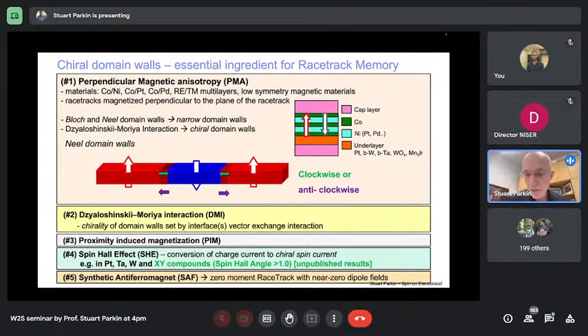That means supercurrent flowing through platinum has a critical current density beyond which it is no longer superconducting, which is different when the current flows from a left to a right niobium electrode placed above the platinum than when it flows in the opposite direction. So this is very exciting. We're doing a great deal of work on proximity-induced superconductivity to create triplet supercurrents that could carry spin angular momentum and therefore enable us to manipulate magnetization at cryogenic temperatures without the use of any energy.